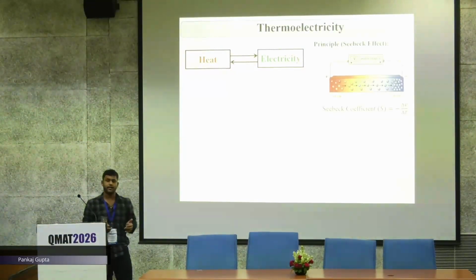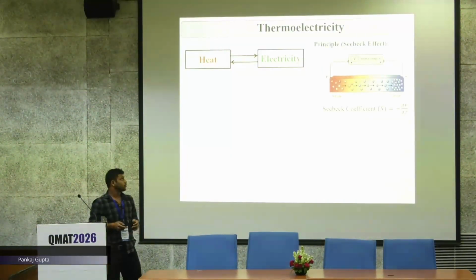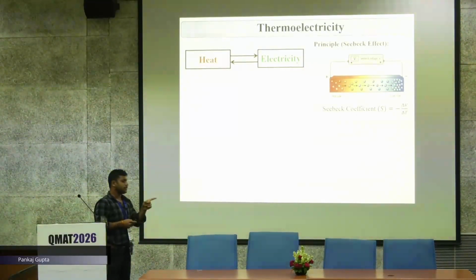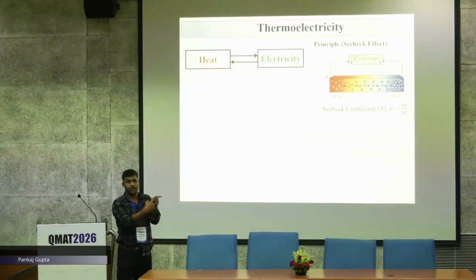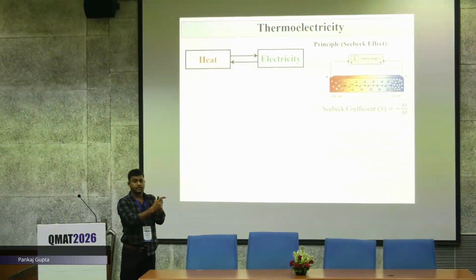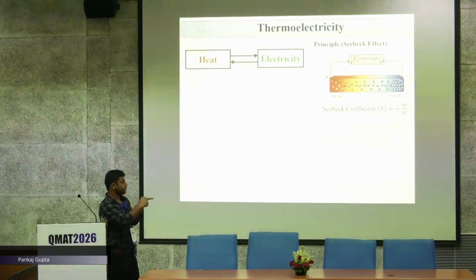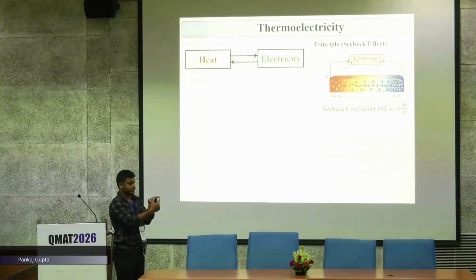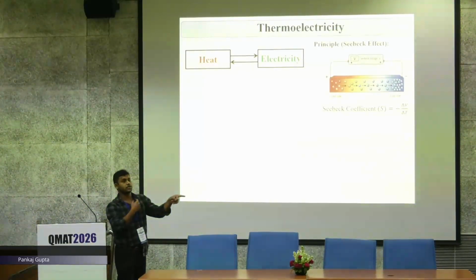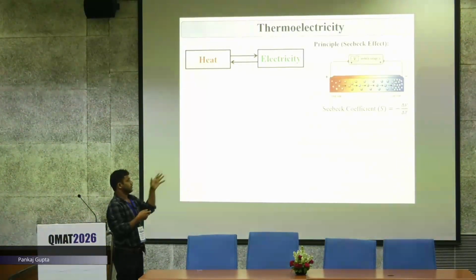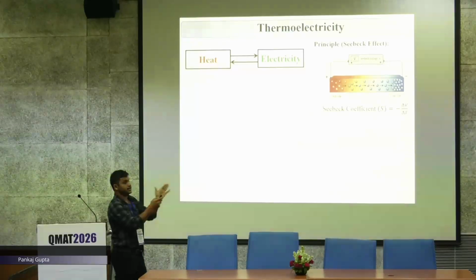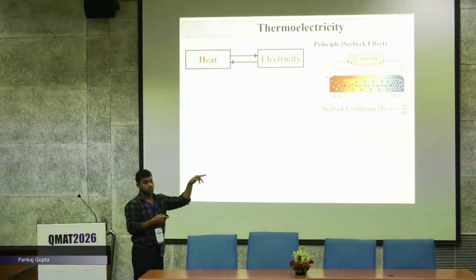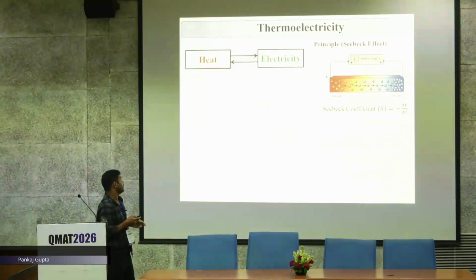So what is the principle behind thermoelectricity? The basic principle is the Seebeck effect. How does it work? Suppose you have a semiconducting material, you heat one end and cool the other end. There is a temperature difference, so the carriers will start moving from high temperature to low temperature, and this will continue until the potential developed at the other end opposes the motion of the carriers. So the potential difference will depend on the temperature gradient. The ratio is given as the Seebeck coefficient, which is a material characteristic property.